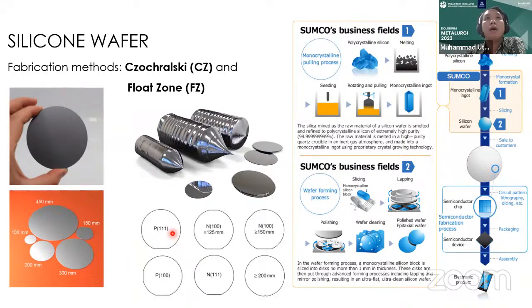And the silicon wafers are usually not fully in a circular shape. Usually they will have 1 or 2 sides that are blunt like this, and there are meanings to those sides, which are the crystalline directions of the silicon. So in here we have different crystalline directions of the silicons, and the way people differentiate each of the products is by having this small dent or side that is blunt. Okay, so this is about the silicon wafer itself.